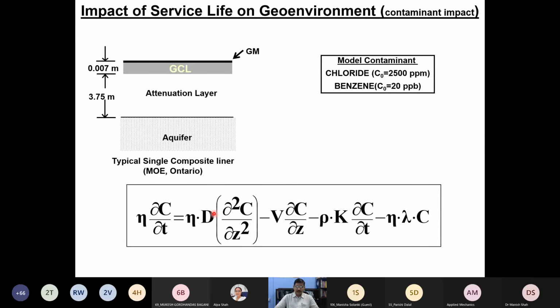Now, how best we can really predict the rate of change of contaminant with respect to time depends on how best we can back calculate and measure the constants in this equation. So this is basically a diffusive term, where D is the diffusion coefficient or the hydrodynamic dispersion coefficient, and V is basically the advective velocity, with porosity, where K is basically the retardation coefficient or the partition coefficient, and where delta is basically the degradation coefficient. For example, organic contaminants degrade by themselves. There is a half-life based on this delta. For organic contaminants or radioactive decay, we can really see the decay term.